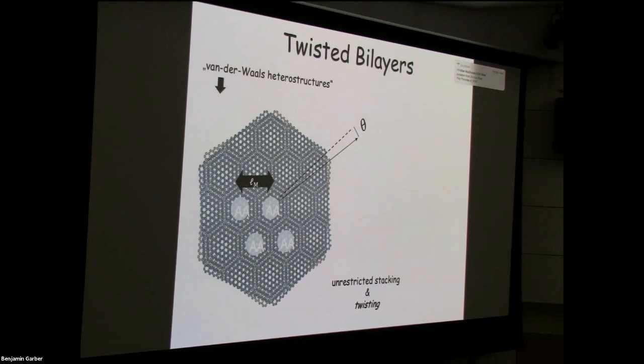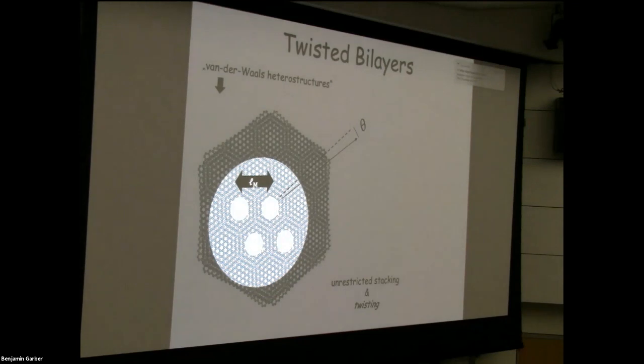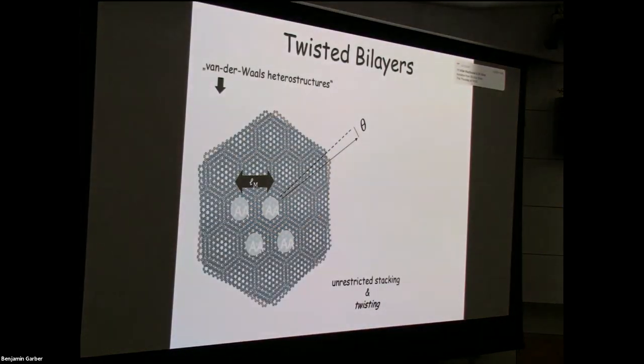And you can see in this pattern open regions labeled AA here that form a triangular lattice, that the stacking arrangement between the layers varies periodically in space when you do a twist. There's a triangular lattice of local AA stacking. And you can identify within each unit cell regions where you have BA stacking of the two layers and AB stacking. So AA stacking refers to the atoms of the two honeycombs all being right on top of each other, and BA and AB to having only half of the atoms in the honeycomb having a neighbor in the other layer. So there's a very clear visual pattern here.